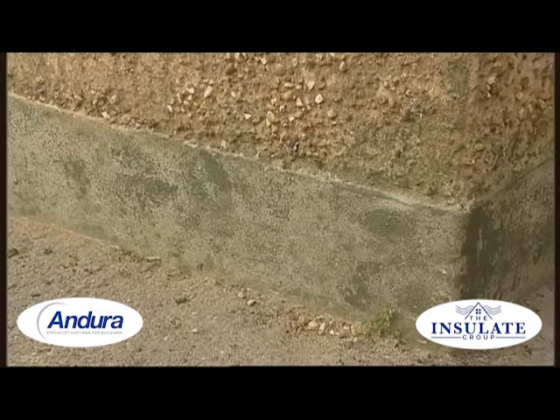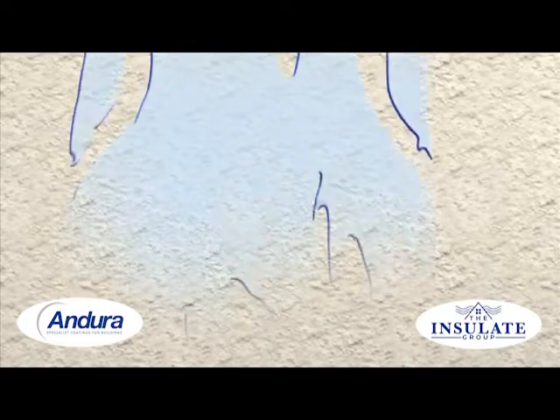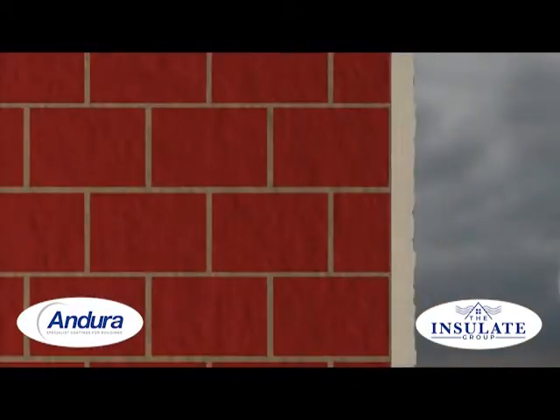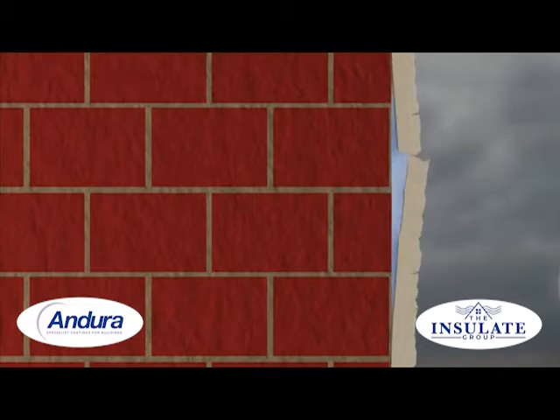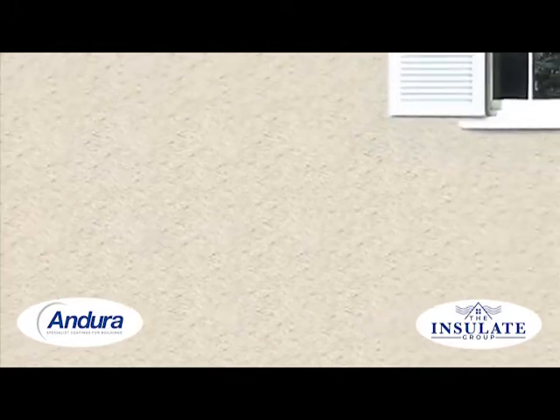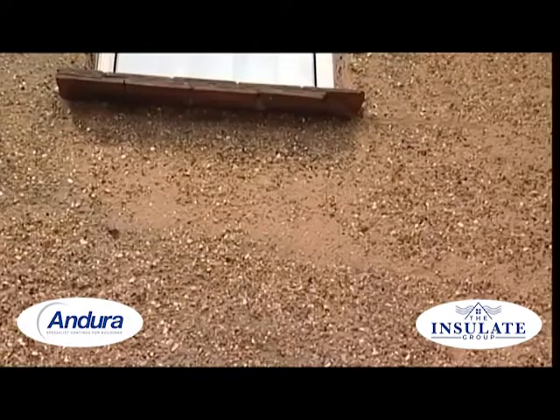The smooth render plinth around the base of this house has algae all over the surface, and this indicates the render is damp. Water is absorbed by porous pebble dash, rendered surfaces, and through ineffective paintwork. Water gets behind the rendered surfaces, and because render is a rigid material and is not flexible, when the water freezes, it forces the render away from the wall and expands the cracks, letting in more water. And so, the damage continues to get worse. The problem is that this so often happens beneath the surface where you don't see it. So, everything looks fine from the outside, but underneath, it's barely attached to the brickwork, and further erosion and damage can occur behind this rendered skin.